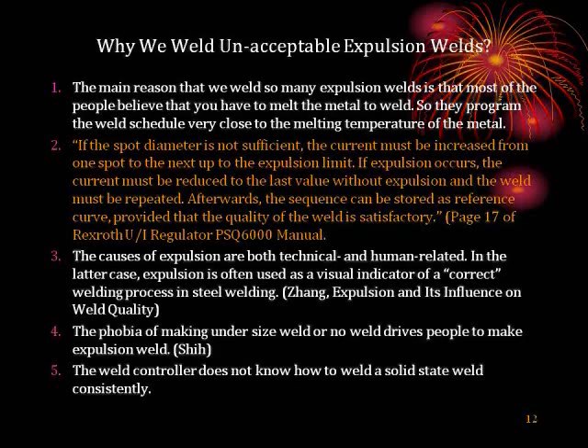Why do we weld unacceptable expulsion welds? The main reason that we weld so many expulsion welds is that most people still believe that you have to melt the metal in order to weld. So they program the weld schedule very close to the melting temperature of the metal. A good example is in the Rexroth PSQ 6000 manual, page 17. It actually recommends you to push it all the way to the expulsion, then back it off one step.